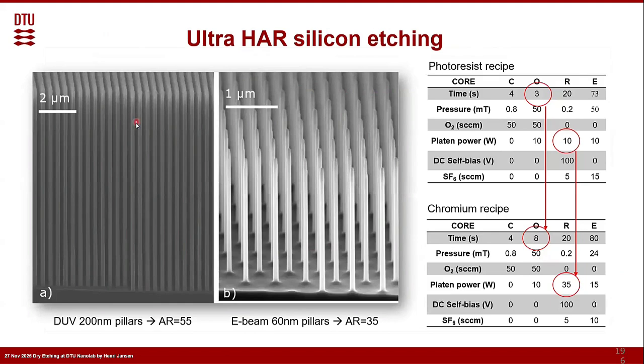we can reach now, because chromium has an extremely high selectivity. And when you oxidize chromium, it is not directly under attack. Not completely true, but much less. And in that sense, you can have a very thin layer of chromium where we can create structures with aspect ratio. Let's say here you see 55 for 200 nanometer pillars, or here for 60 nanometer pillars.